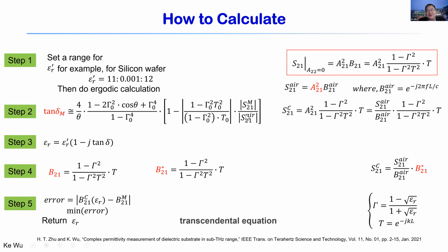Then you end up with the loss, the actual measurements. Those S21 with materials and S21 with air are the port-to-port measurement results. All those equations, the other part of this loss tangent equations, come from the computational model. It's a multi-reflection model. So you see these loss tangent parameter extractions come from the combined analytical models together with the measurement results. This measurement result is explicit. So in this case we can develop very simple analytical equations, which allow us to extract the loss tangent of low loss materials.